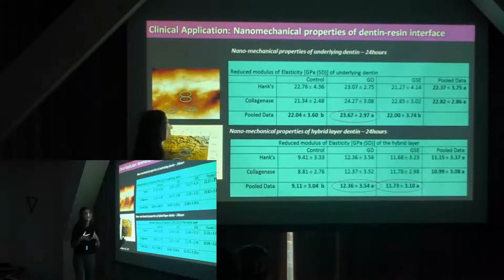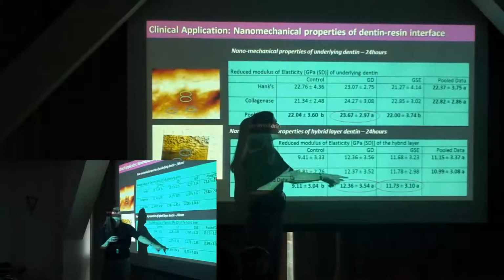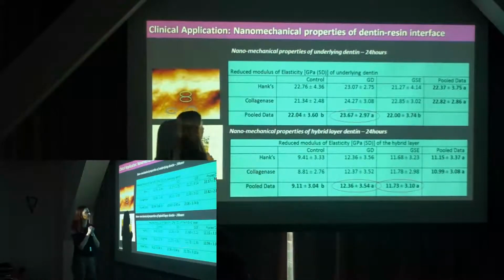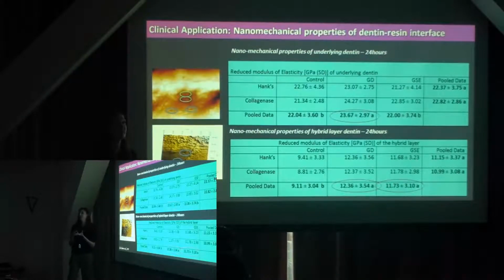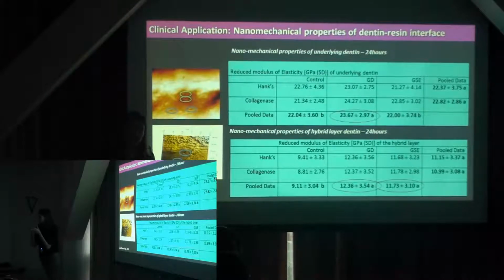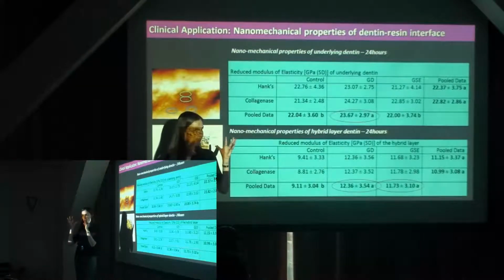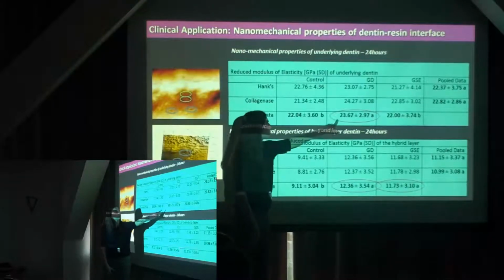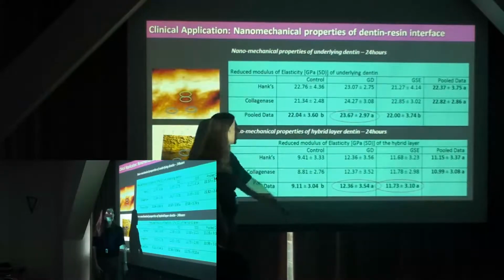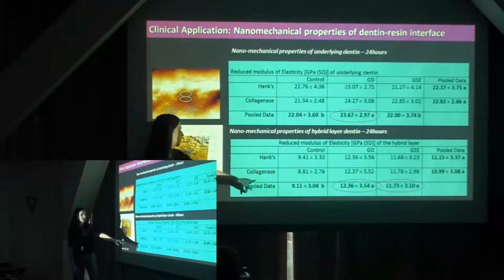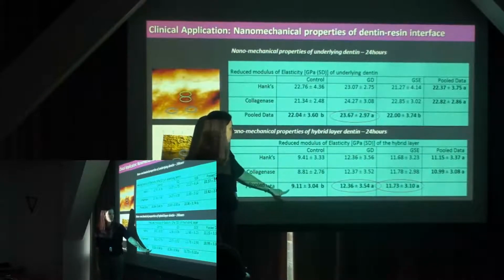And what we notice is that glutaraldehyde, for example, increased the modulus of elasticity of the underlying dentin too, because it really has the ability to infiltrate even a mineralized tissue. While these proanthocyanidins are higher molecular weight, so they don't have the same ability. So we've seen a more significant effect in terms of the underlying dentin for glutaraldehyde. The grapeseed didn't have any major effect. The hybrid layer was around 9 gigapascal for the control, and it went up significantly for the two groups.